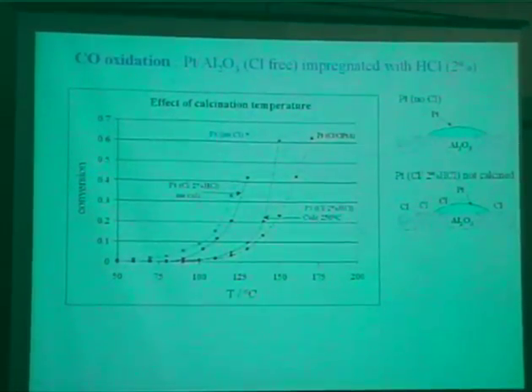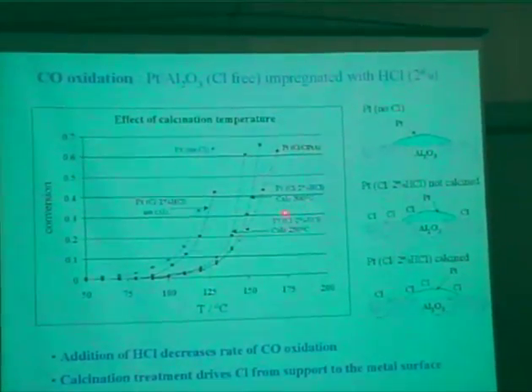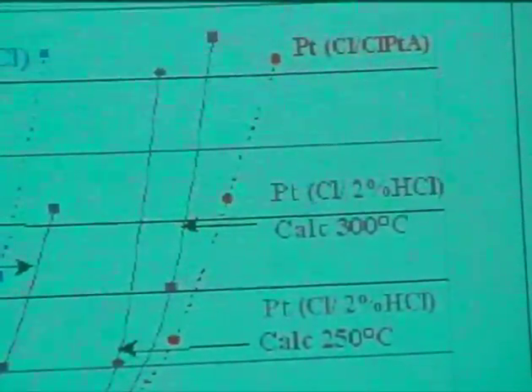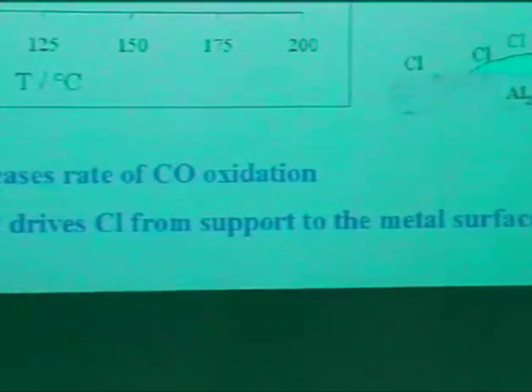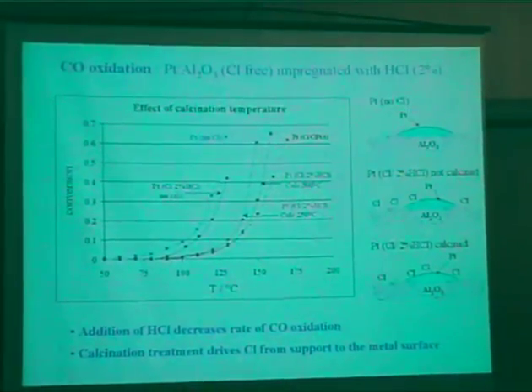And if you keep playing with this, now we did it at 300, more of the chlorine went onto the surface and had the same effect as when you started with the chloroplatinic acid catalyst. So it turns out that the calcination drives the chlorine from the support onto the metal. And you can ask yourself the question, can we do the reverse? And the answer is yes. So you can drive the chlorine off the metal and into the support again, and back and forth. So it's pretty tricky to get rid of all of it.